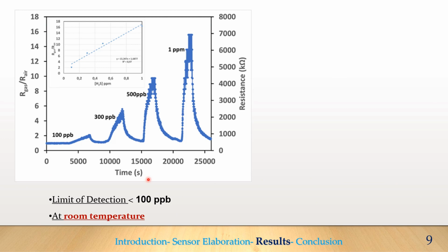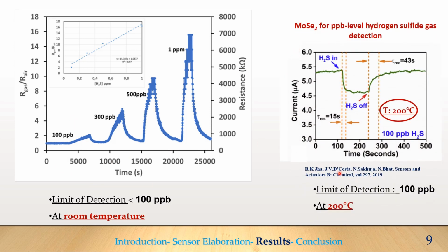Herein, the electrical response recorded at room temperature for the MoSe2-Mo2C based sensor for different H2S concentrations. The sensor resistance is shown to increase when the concentration of H2S is increased, with enhanced sensitivity. These results demonstrate that the sensor behaves as a p-type semiconductor material. The sensor shows high sensitivity to H2S from very low concentration. 100 ppb were detected at room temperature, as compared to the literature for a MoSe2-based H2S gas sensor, where the operating temperature is 200 degrees for the detection of the same concentration.